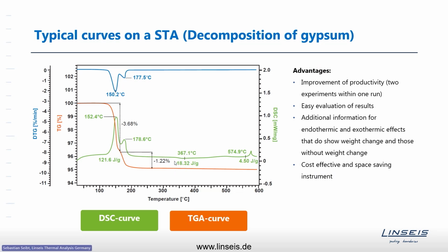In the further curve, at higher temperature, you see there is some additional effect, and even another one. These are effects that do not show a mass change. The simultaneous signal of the mass stays constant. So out of this, you know that these must be phase transitions or melting. In that case, it's a quartz transition up here at around 575 centigrade. This is also a phase change within the material, and you know that because there's no mass change. Phase transitions, from liquid to solid or from one phase into another, usually do not show a simultaneous mass change. A decomposition reaction, however, does show that. And that's how you can identify effects and get information out of your sample run.